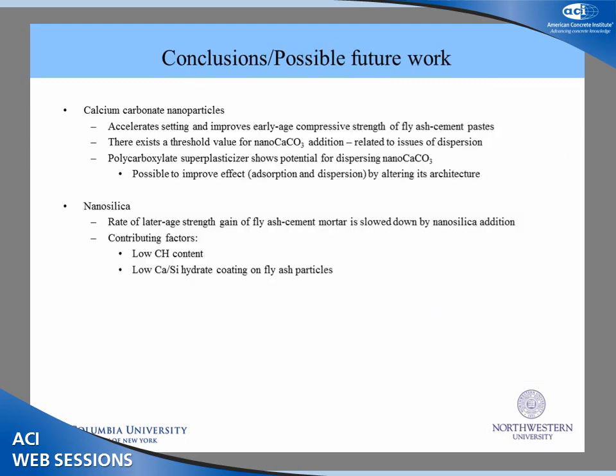So in conclusion, the calcium carbonate nanoparticles did accelerate setting, and it did improve the early age compressive strength gain of fly ash cement paste, but there did exist a threshold value that was tied to issues of dispersion. Polycarboxylate superplasticizer did show potential for dispersing calcium carbonate, and this can probably be further improved by altering the architecture of the superplasticizer. And with nanosilica, the rate of later age strength gain was diminished a bit over time, and this is tied to low CH content due to the high CH consumption by the nanosilica at early ages, and then also the low calcium silicate hydrate coating on the fly ash particles.